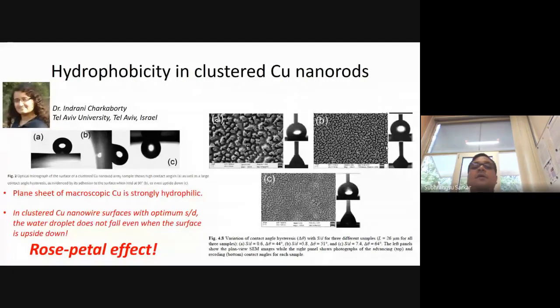Now it's a bit interesting because if you take a copper nanowire, and if you take a plain copper thin film or a plain copper solid, which has been chemically cleaned, it's extremely hydrophilic. You drop a little bit of water and the water spreads immediately. It is hydrophilic because this copper surface has free electrons, and that likes to attract water and make bonds with them. On the other hand, the same metallic copper, when you make these kinds of structures, does not allow the water to go in. It behaves like a super hydrophobic material with a contact angle of approximately 160 degree. But on the other hand, if you tilt the sample completely upside down, the water doesn't go away either.